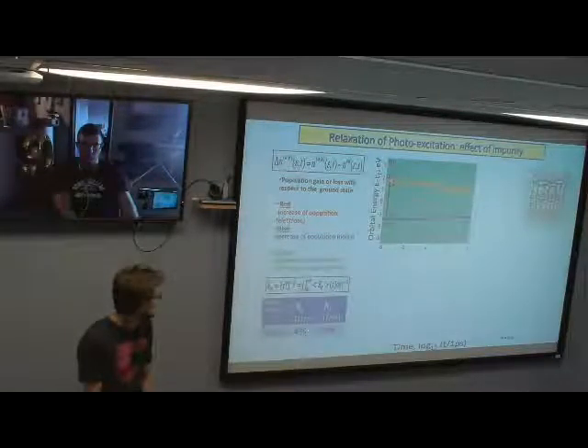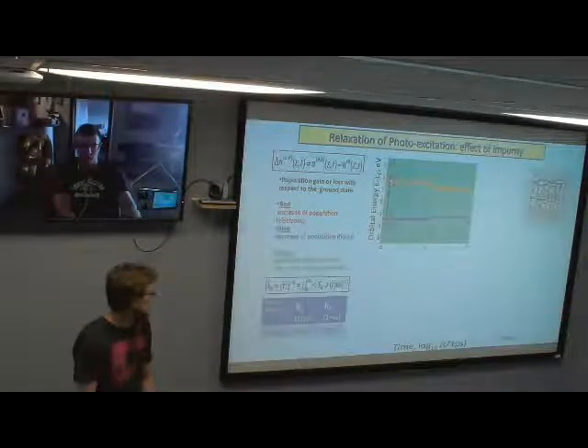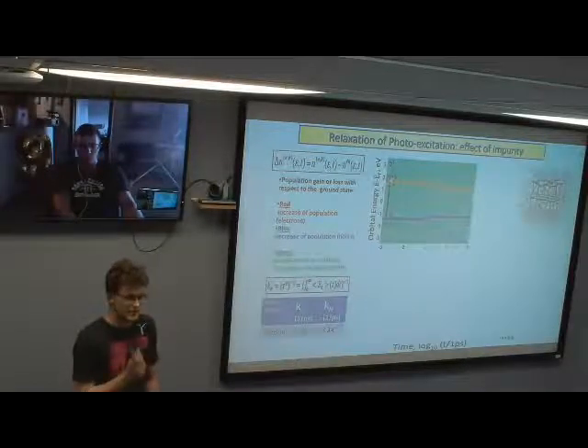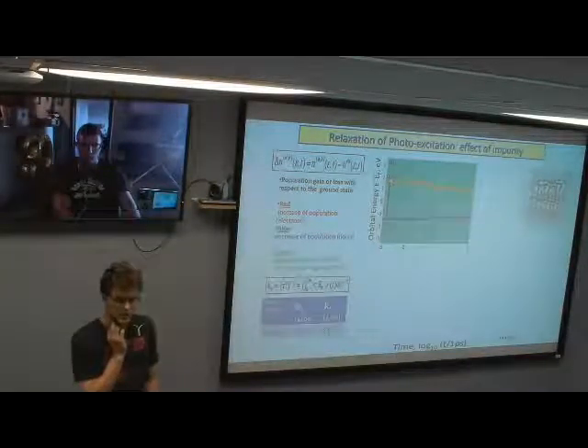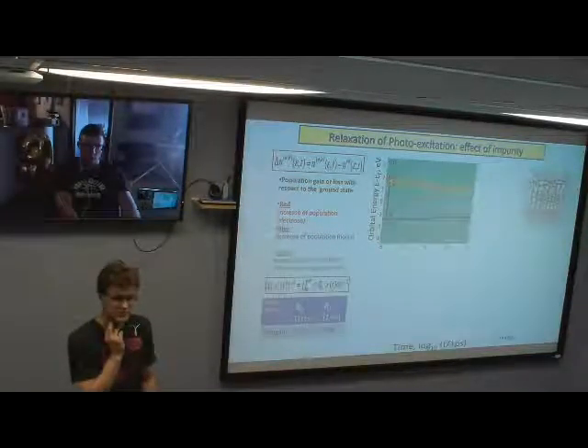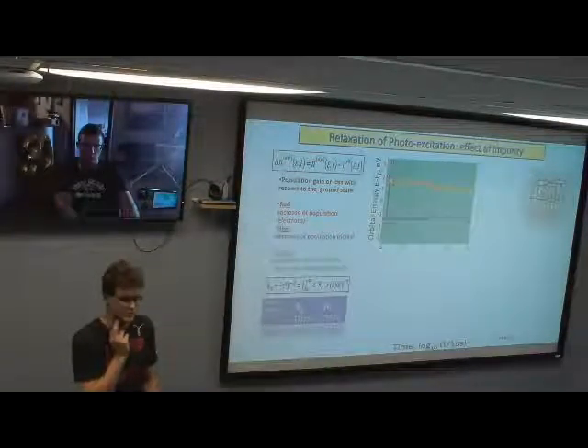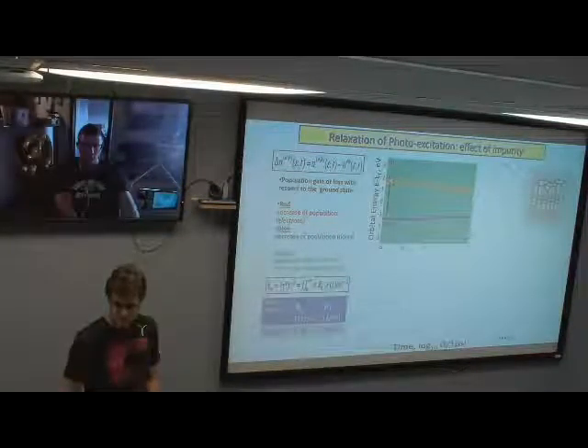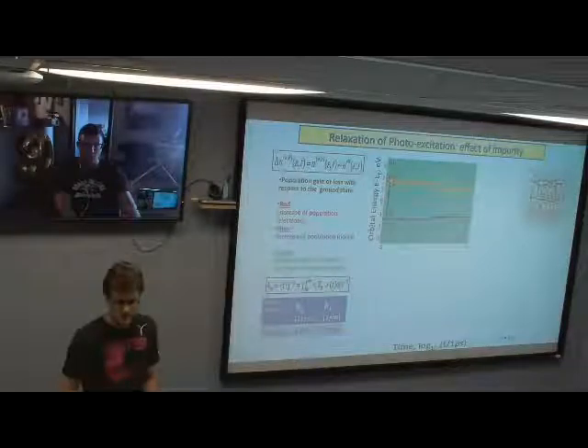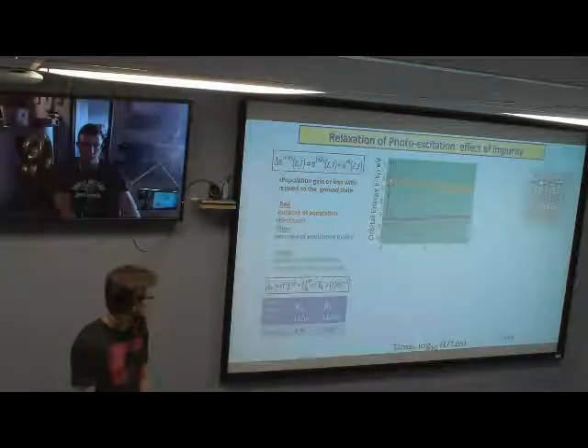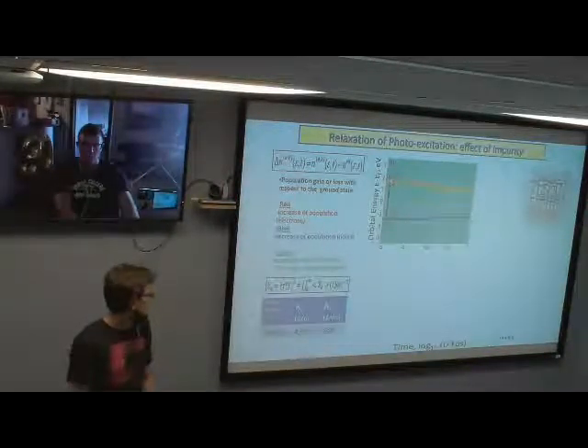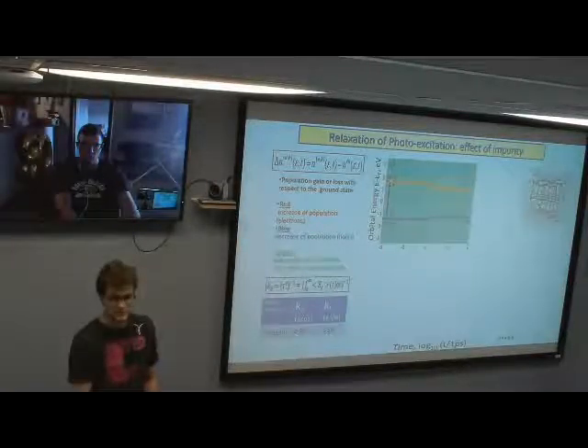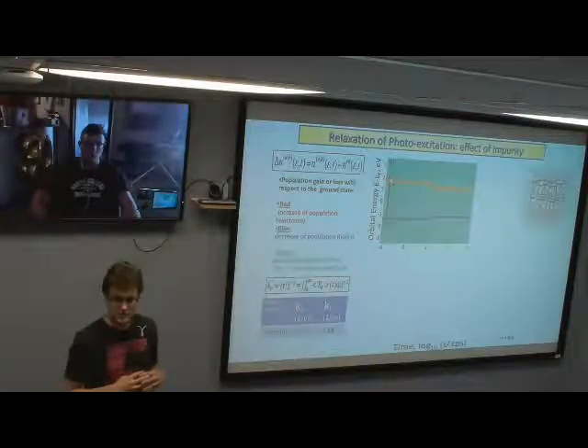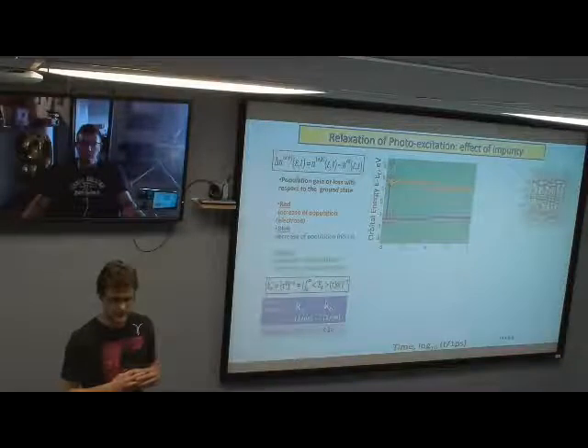And so I didn't put them on this slide, but experimentally, or the reports I've seen anyway, hot carrier cooling usually occurs on sub-picosecond timescales, but it's more in the range of like 400, 500 femtoseconds. And variations in that could just be due to our model size. Since it's smaller, we have more ligand interactions than what you'd see experimentally.